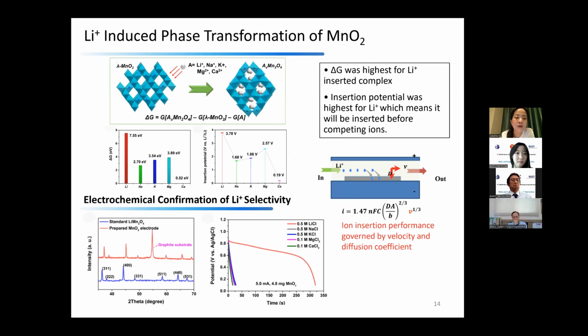Seawater contains lithium, sodium, potassium, magnesium, and calcium. We can see from these figures that different ions have different free energy towards this manganese oxide, and lithium has the highest. That means when lithium is inserted into the complex, the largest amount of free energy is released. That means lithium will be very stable after being inserted and combined with the structure, and that is one of the particular reasons the structure has selectivity towards lithium.